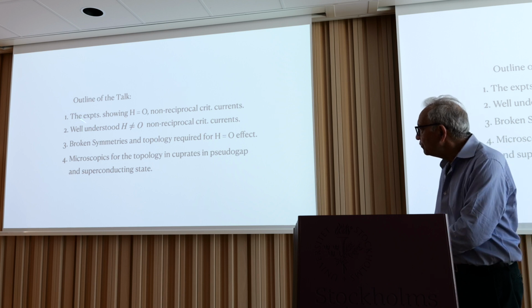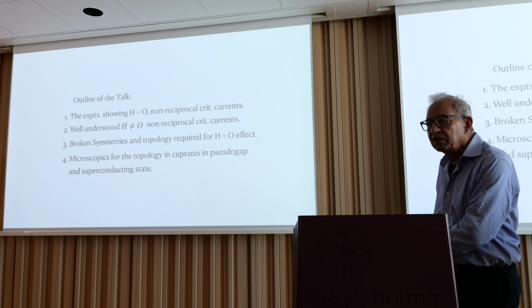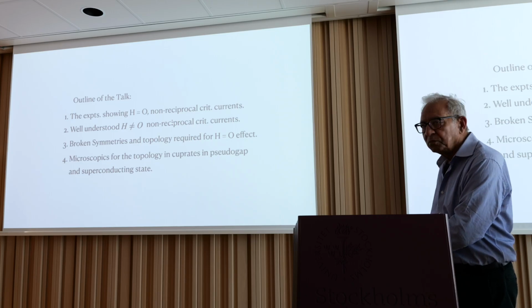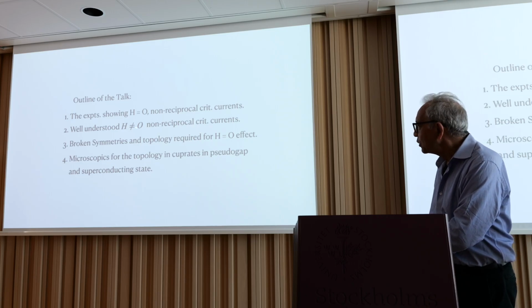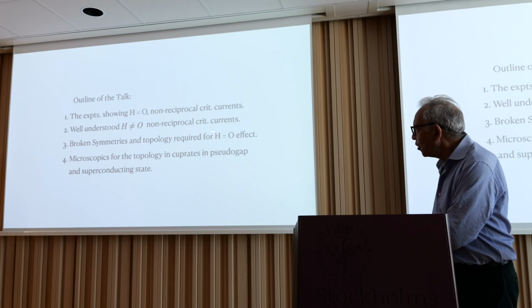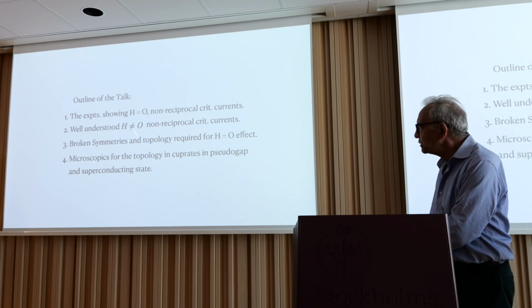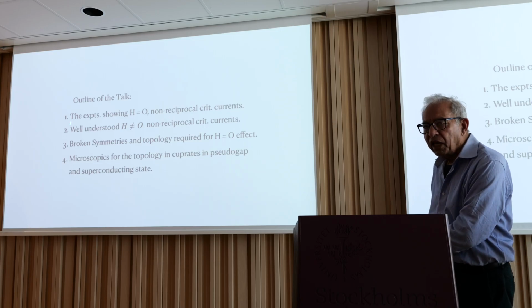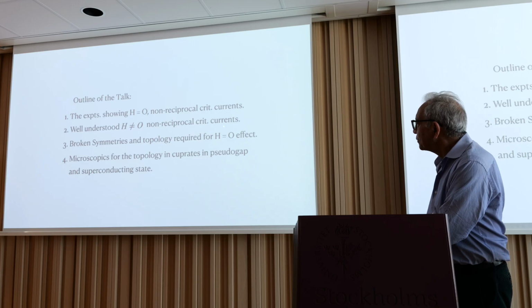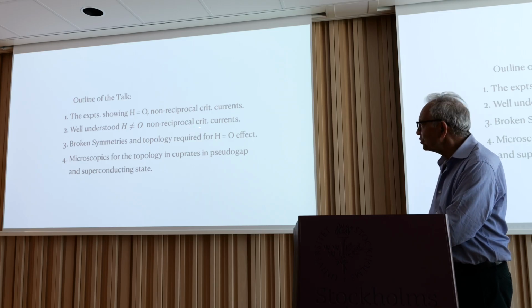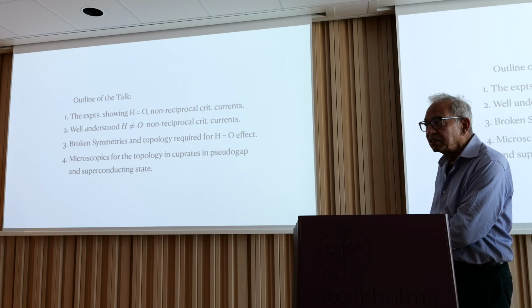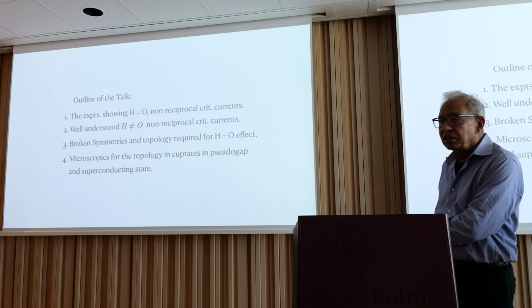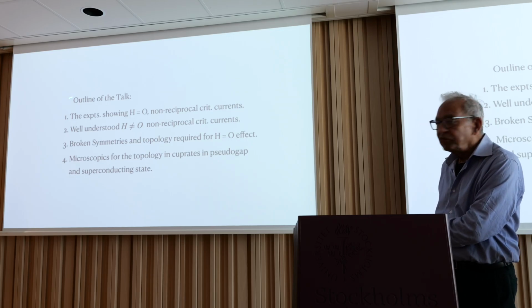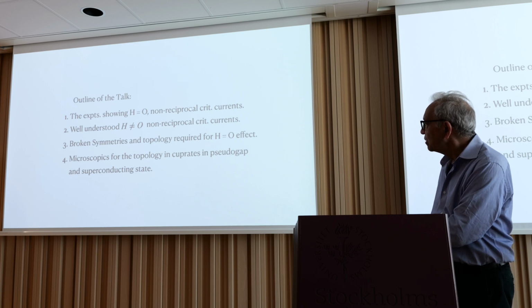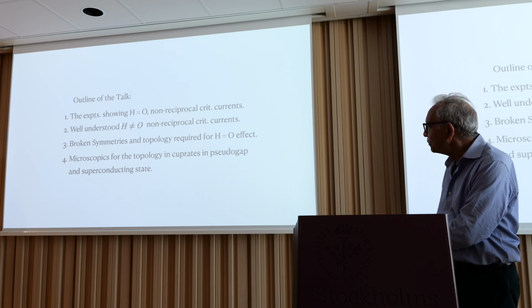I will briefly mention the very well understood finite field non-reciprocal critical current, because if we know about this, we can say that the symmetries which are produced by applying a magnetic field to observe non-reciprocal critical currents should spontaneously happen in the case of the zero field non-reciprocal critical currents. And that's what I'll talk about here.